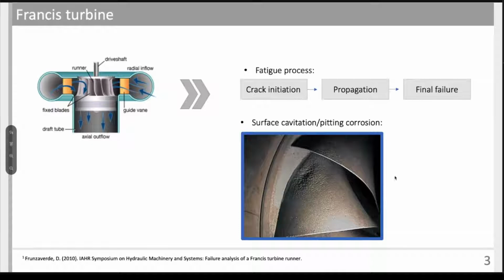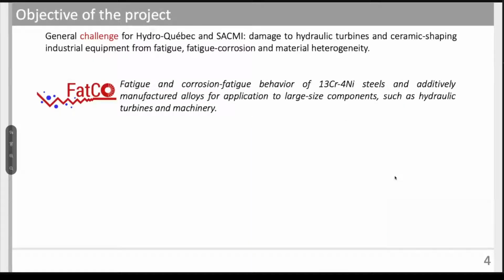And it can also present surface cavitation and pitting corrosion that is caused by the flow of fresh water on their surface. And these are ideal nucleation sites for cracks. So here highlighted in blue, we can see an example of a turbine blade with surface cavitation and pitting corrosion. So in order to minimize these problems, several studies have been carried out with the objective of developing new materials for the construction of rotors, and also the recovering of these cavitated regions. So, as a continuation of Hydro-Quebec's research study, a bigger project entitled FATCO was designed.